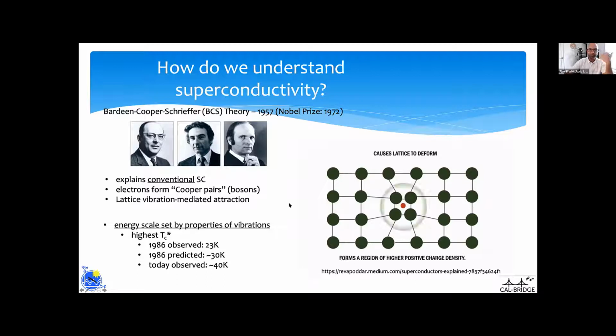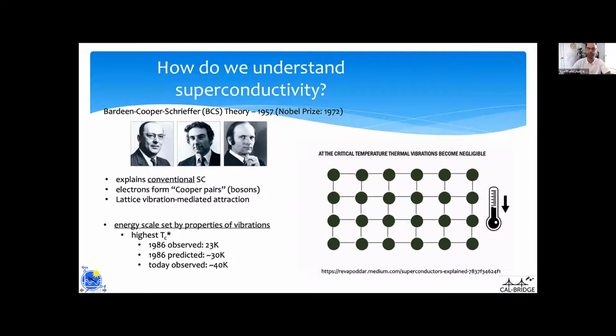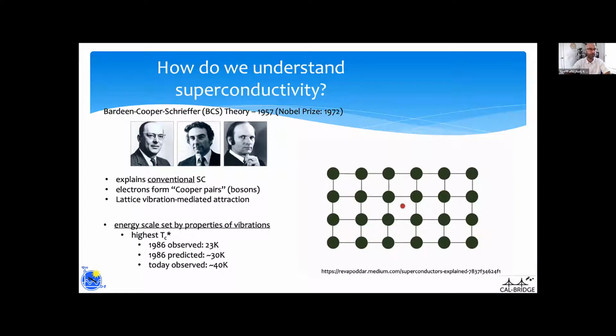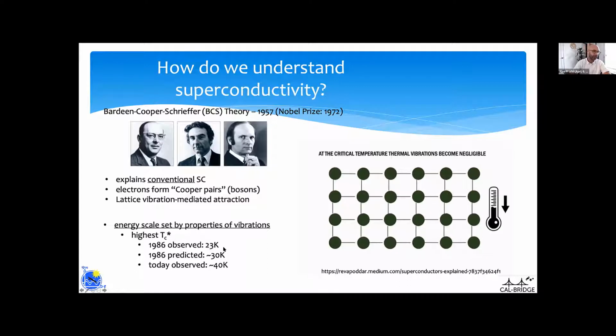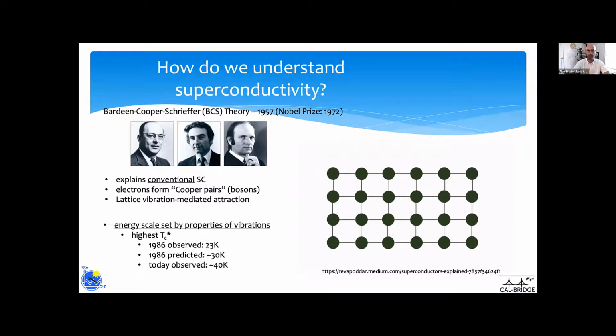This theory was very successful, and it predicted that there was some kind of high limit to the transition temperature of materials. Using this theory in 1986, it was predicted that the highest transition temperature would be 30 degrees Kelvin, which is not that high. You can imagine that's pretty close to absolute zero. It's hard to cool things down to that temperature. So this conventional theory only predicted materials to be superconducting to around 30 to 40 Kelvin.